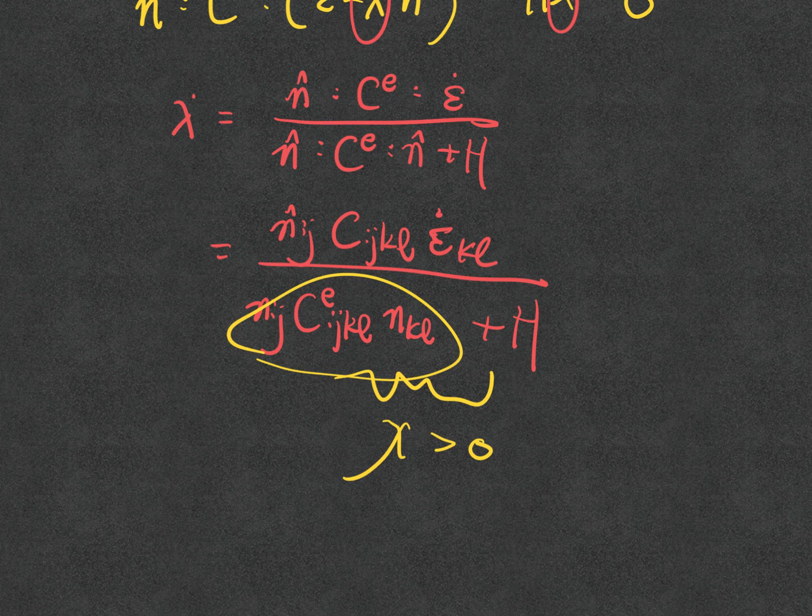Your positive multiplier is monotonically increasing for given reasons. You can develop more plasticity, but if you dissipate more work, you cannot make the material more elastic, okay? You see what I mean? So what it means if it's negative is the following. The strain goes in one direction and I develop the plastic strain in the opposite direction, which is equivalent to saying that I make the thing more elastic. So that makes no sense, okay?